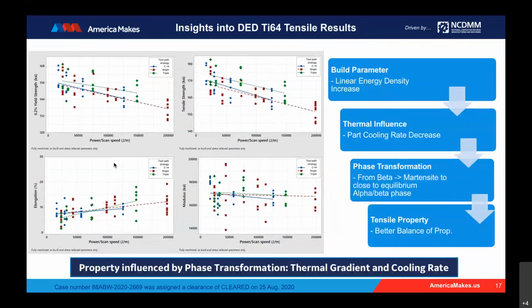So here we were looking at linear energy density and the influence of this varying linear energy density upon the different performance metrics. So one thing that was clear was there appears to be a downward trend for both yield and ultimate strength measurements with increasing linear energy density. However, you can see that there's quite a bit of scatter here. This scatter is because of the anisotropy within the material. So if you were to segment this data set by test orientation, you'd see the scatter go down at each linear density.